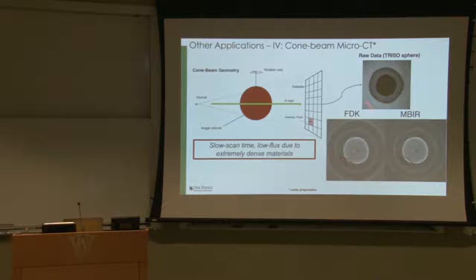It's all attenuated. At the center, it's a chemical, some compound of uranium, so it just densely attenuates. But they're interested in studying how these particles are inside, using CT. So it's really difficult to take this raw data and just get a good reconstruction out of it. And it's a layered particle. It has a core with a bunch of layers around it. So how do we get high quality CT reconstructions? Because if you use the standard techniques, since these beams are so highly attenuated, you start seeing a lot of streaking artifacts.